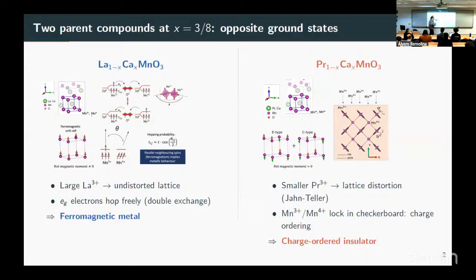magnetic interaction. The type of interaction that this controls is that by itself, it has a phase coexistence of regions where it's rich in manganese 3+ and other regions that are rich in manganese 4+. Depending on the ion that is there, the driving orbital is different, and in an overall picture you have chessboard-like domains. So you have these particular orbitals aligning with the manganese 4+ in this way, creating a ferromagnetic strong correlation, or antiferromagnetic strong correlation if the orbital is more or less perpendicular to it.